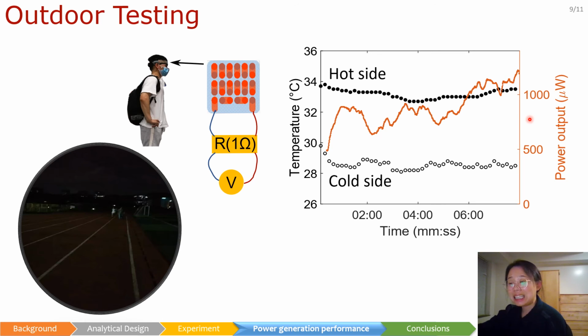We notice, despite some fluctuation in the power output curve, the average power curve increases with time due to better heat dissipation at the cold side of the device and potentially increased metabolic heat at the hot side during running. Overall, the output power density aligns with the measured temperature difference between the hot side and the cold side. Besides, we notice in outdoor testing that the fabrics also hold up well against sweat.